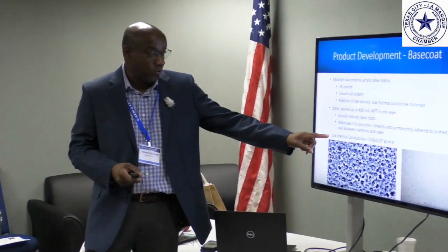So this is a photograph of what it looks like. That's an SEM image. So you see there's quite a bit of pores in that material, giving us a lower thermal conductivity of 0.06 to 0.07. And again, the lower the number, the better the insulation efficiency. The lower the number, the better the insulation, the thinner the coating. So a lot of the coatings in the market today are between 0.08 and 0.1 for thermal conductivity. Therefore, they have to apply several coats to get to a good thermal efficiency.